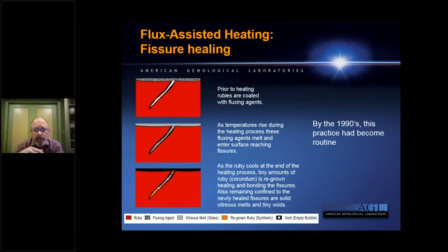This is just a quick diagram to help describe how this process takes place. They'll coat the stones with a kind of slurry of fluxing agents before heating. And as they heat it, as the temperatures go up, the fluxing agents will melt, they'll flow over the surface of the stone, they'll penetrate into fissures. And what they actually end up doing is they partially dissolve the contact with the corundum. So it actually draws alumina into the melt as you're raising the temperatures and as you're holding the temperatures. And then as you're ramping down the temperatures, you actually facilitate the regrowth of corundum. So it starts to form as you're ramping down the temperatures.